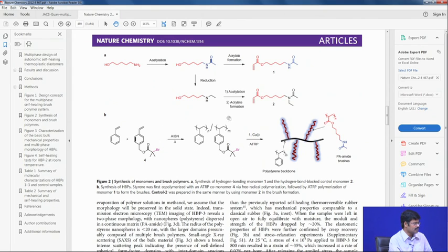Now, this is a macro initiator, and you are reacting this macro initiator with this monomer, and that is an ATRP reaction. You are using copper 1. So, with this ATRP reaction, since the reacting center of the macro initiator, which is masked by the bromine, is at the side chain, your chains will grow from the side chain as this soft brush, and then ultimately you get this kind of architecture, depending on how much of this moiety you are using.